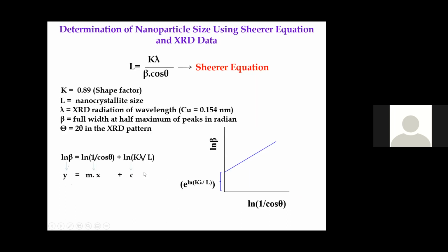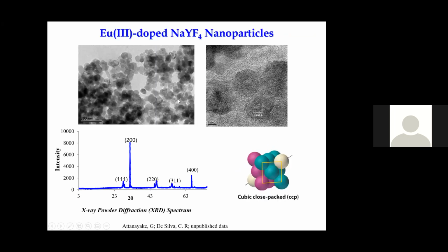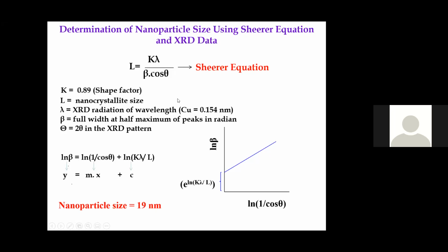This X-ray diffraction pattern can also be used to figure out the size of the crystallite. That means the size of one crystal dimension in this nanomaterial. We call it the Scherrer equation, and there's a shape factor, and we get the nanocrystallite size by using the wavelength of the X-ray light. If we use copper light, it's 0.154 nanometers. Then we measure the full width at half maximum of the peaks, and you know the two theta value, so we can get the theta. So we can use this equation to calculate the crystallite size of these nanoparticles. We calculated it to be 19 nanometers. It's a very tiny, small nanoparticle that we are talking about here.